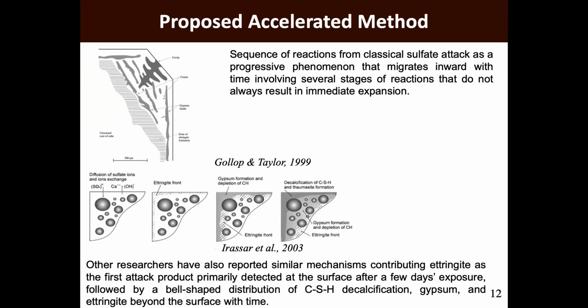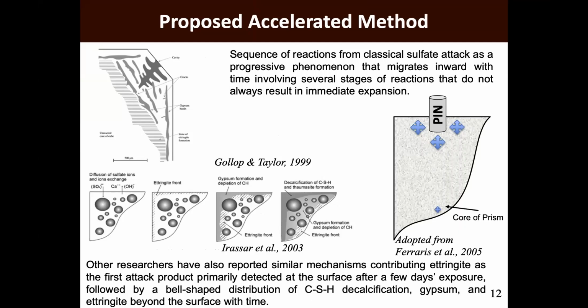And so the idea of sulfate is really based on the ingression of chemicals that causes chemical reaction. The difficulty with this is that it's a diffusion-based system. In other words, it takes time for the reaction to occur, cracks to develop, and then further ingression to occur. And when you think about measuring expansion, a lot of times you may be measuring expansion near the pin, while the actual center of the sample may be undetected. In other words, you don't have much of the deterioration that may be occurring in the sample actually being measured, right? So this is what draws us to our particular type of method.